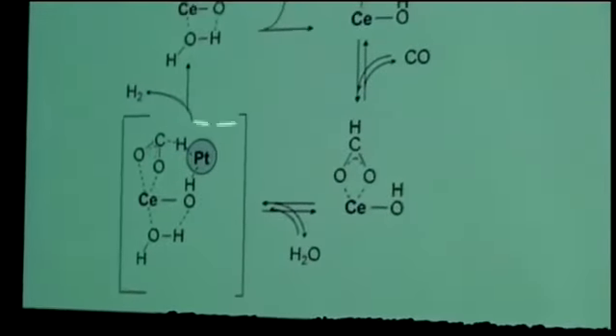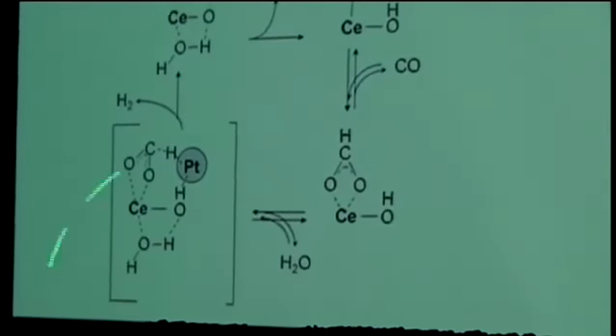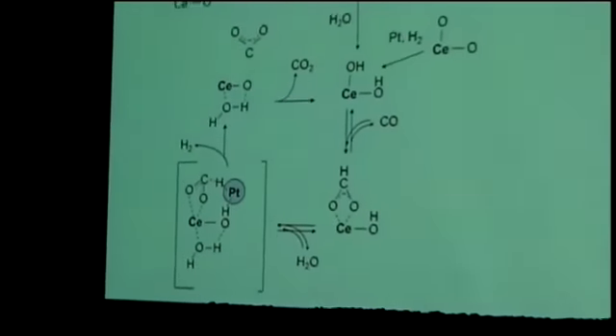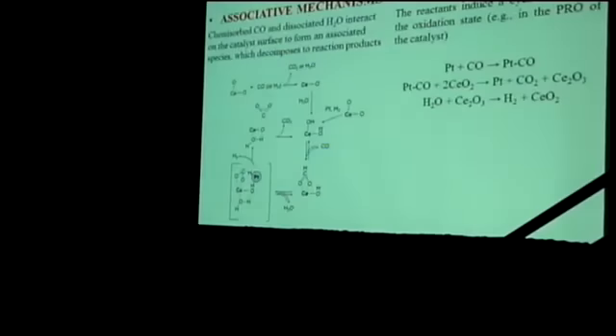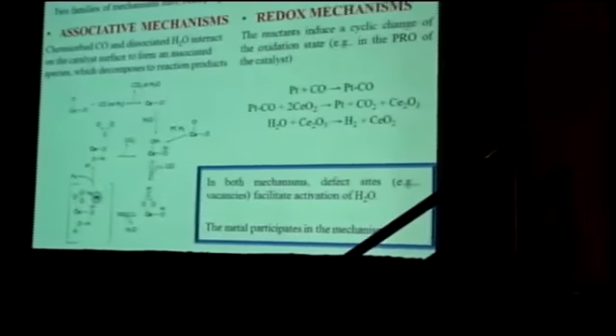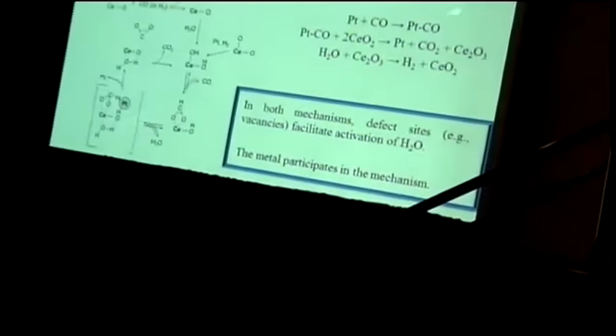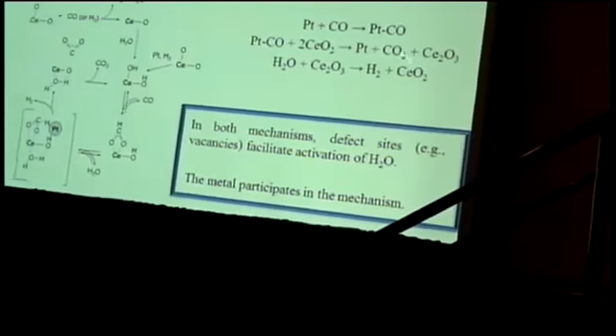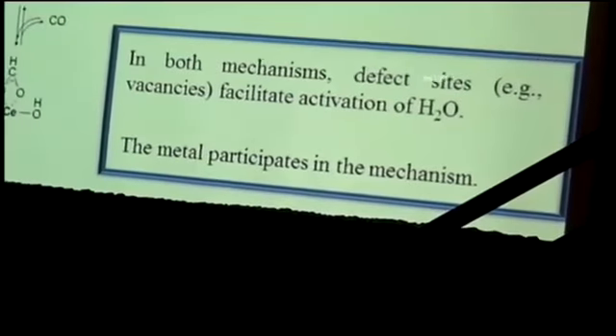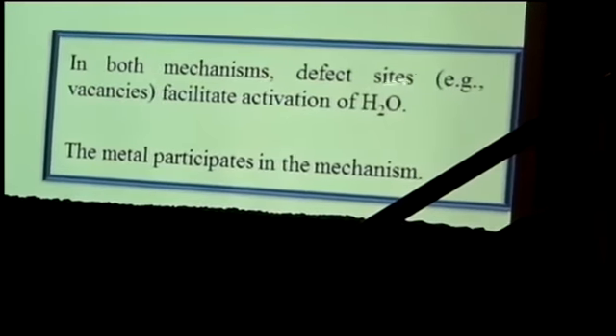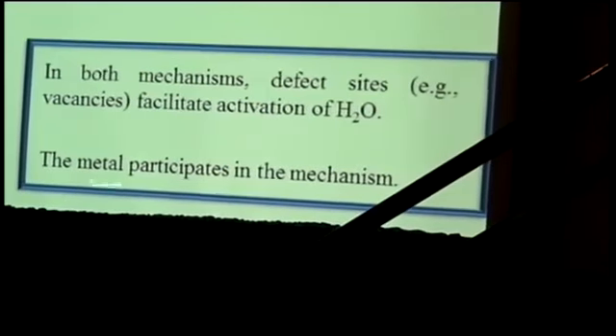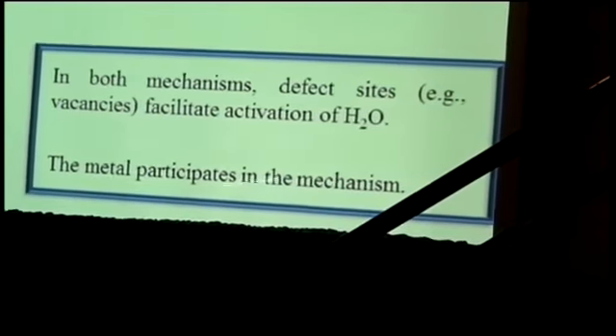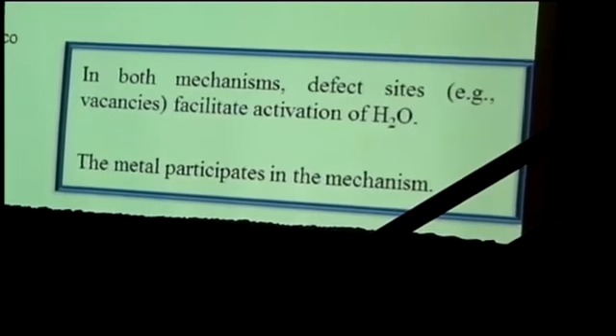You can see that the steam is actually participating in the rate-limiting step of the decomposition before it undergoes dehydrogenation. Also, the metal is involved, so this is occurring at the metal support interface and liberating hydrogen and CO2 in the process. So you can see there are some similarities actually between these mechanisms. A lot of people talk about the differences, but there are similarities in both mechanisms. Defect sites are involved for activating water, and in both cases the metal at the metal support interface is participating in the mechanism.